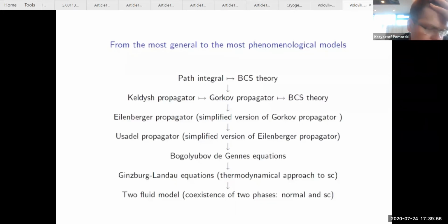This also motivated many people to implement qubits in superconductors and superfluids and not in other systems. Indeed, in superconductors we have very low noise, about 3 orders of magnitude lower than in semiconductors. That's a very good argument for using Josephson junctions and low temperature superconductors in quantum information processing.